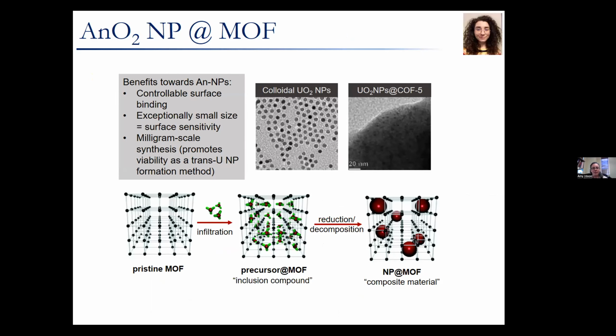And the final piece of research that I really wanted to talk about today is coming out of Washington State University, where they're looking at incorporating actinide dioxide nanoparticles in the pores of a metal organic framework. The reason they're using actinide nanoparticles is because they're able to control the surface binding. You can synthesize them at a wide variety of sizes, which means we can make them very small and therefore very sensitive to the different pores of a MOF. And we're able to have milligram scale syntheses of these types of material, which means that hopefully we'll be able to move past uranium dioxide and into the transuranic sometime soon.